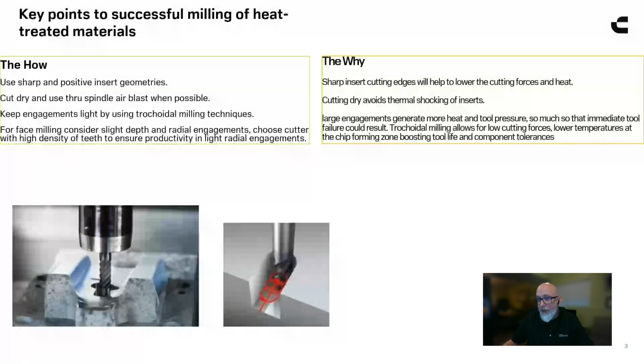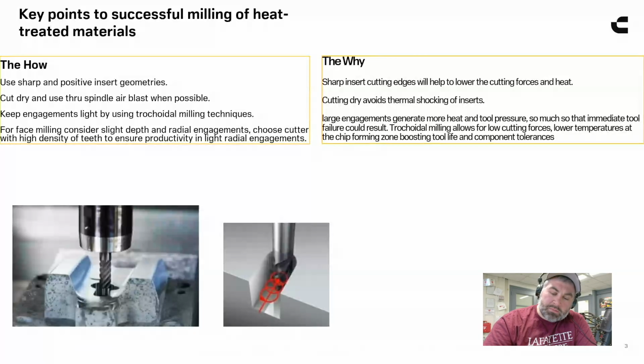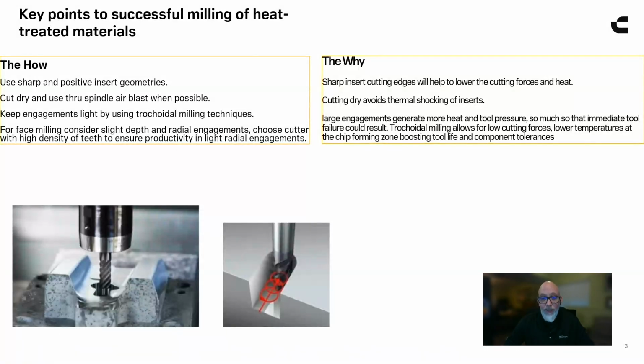Moving onward from that, we talked about how important it is to have that sharp edge, but also how important it is to really feed that lightly. And let's just say that we've got to do a slot. If you were putting an end mill through a piece of regular ISO P, maybe 1018, you could theoretically full slot that. You're not going to have too many difficulties. It might not be the best way to do it still, but you could get through it, right? If you try that in this heat treated material, you're going to generate way, way, way too much heat. It's going to work harden the material. You'll have almost instant tool failure.